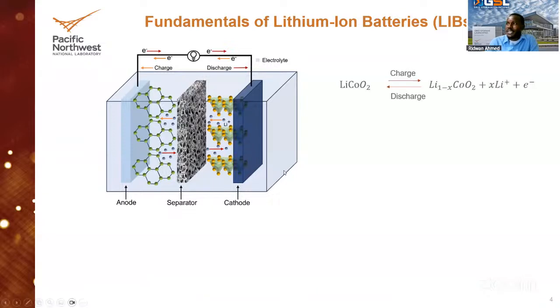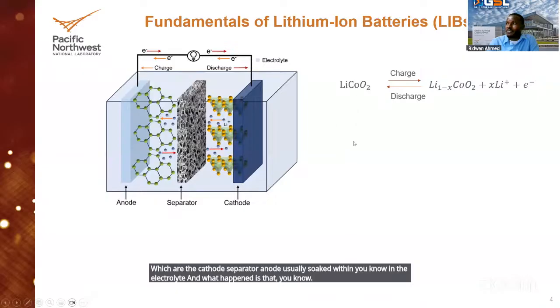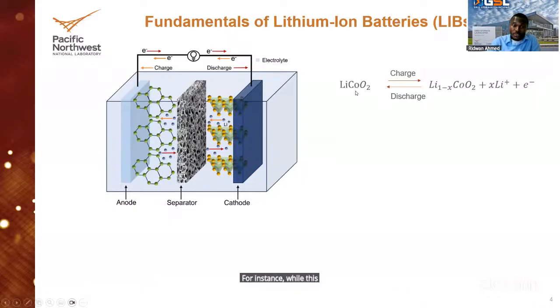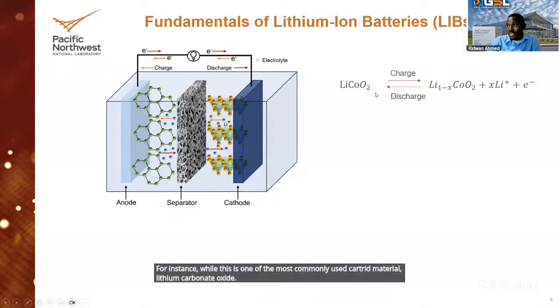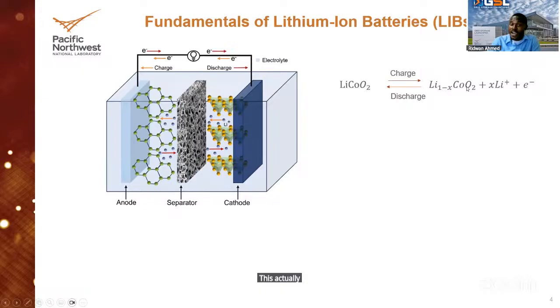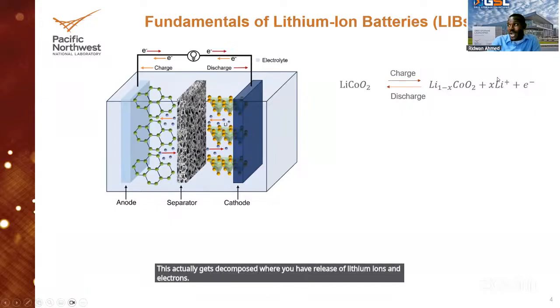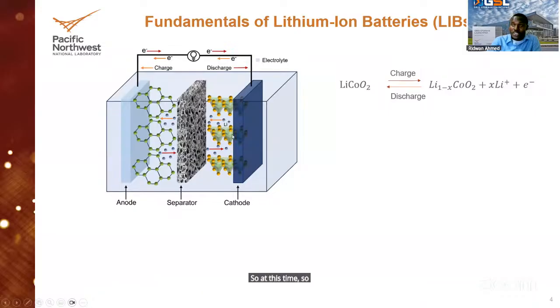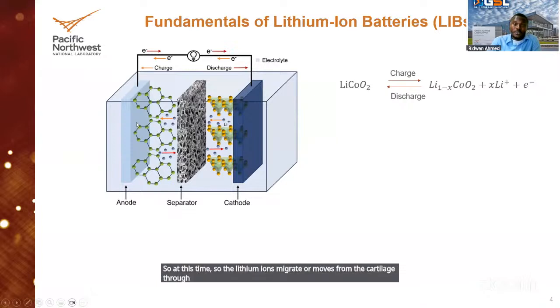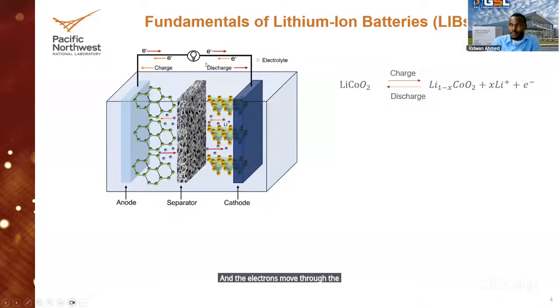And what happens is that when you're charging your battery, you have these cathodes. For instance, this is one of the most commonly used cathode materials, lithium cobalt oxide. This gets decomposed, releasing lithium ions and electrons. At this time, the lithium ions migrate from the cathode through the separator towards the anode, and the electrons move through the external circuit.